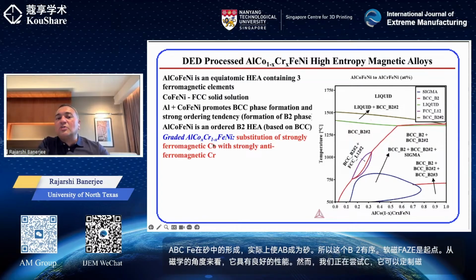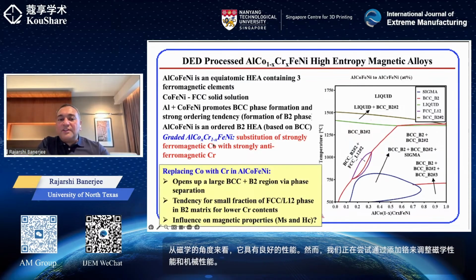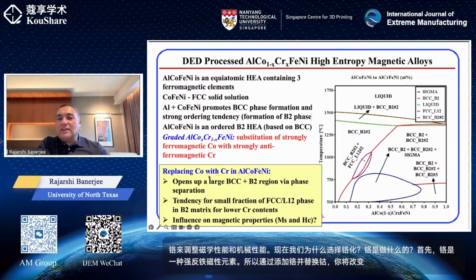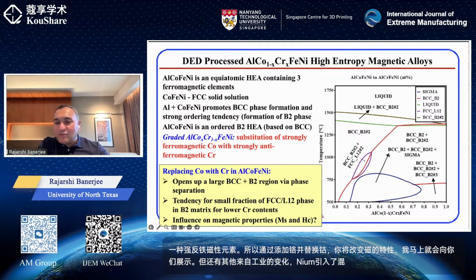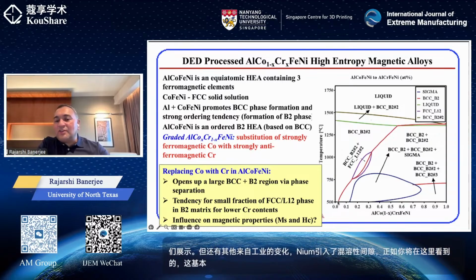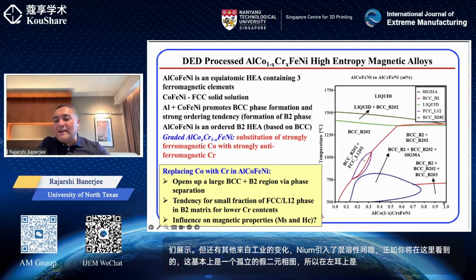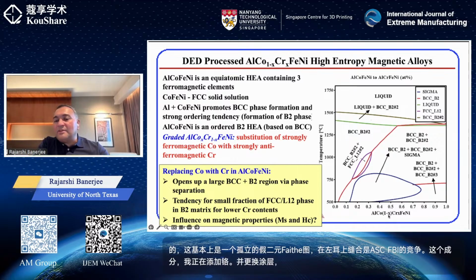Now, why are we choosing chromium? Well, first of all, chromium is a strongly antiferromagnetic element. So by adding chromium and replacing cobalt, you're going to change the magnetic behavior, which I'll show you in a minute. But there are also other changes chromium does. Chromium introduces a miscibility gap, as you will see here. This is basically an isopleth, like a pseudo-binary phase diagram. On the left here is the AlCoFeNi composition, and I'm adding chromium and replacing the cobalt. So we increase chromium and reduce the cobalt.